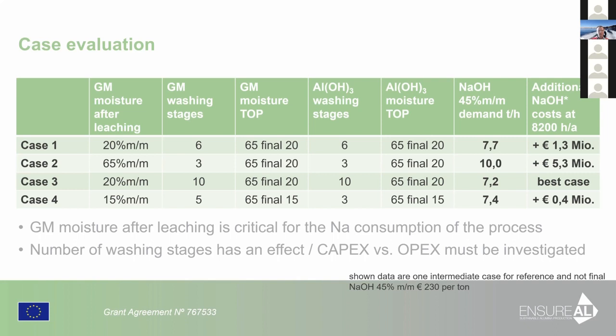Then I also changed the number of washing stages within the case study. So I have 6, 3, 10, and 5. And these moistures, 65 and 20%, mean here the first stages of thickener, where you just pump the slag from thickener to thickener, which means you have a very high moisture with 65%, and the last stage is then a filter press or so on, so that you have then the 20% of moisture. And the same is valid for the alumina hydroxide washing.